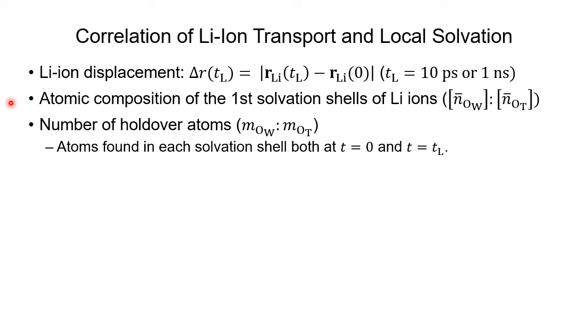We have also investigated the correlation of lithium-ion transport and the local solvation structure and dynamics. First, we determined the lithium-ion displacement delta R, like this, using the short time span. And we calculated the atomic composition of the first solvation shells of lithium ions. That is the average number of OW and OT in each solvation shell over a short time span. And to study the dynamics of lithium-ion solvation, we calculated the number of holdover atoms, MOW or MOT, that is the atoms found in each solvation shell at the beginning and end of a short time span.